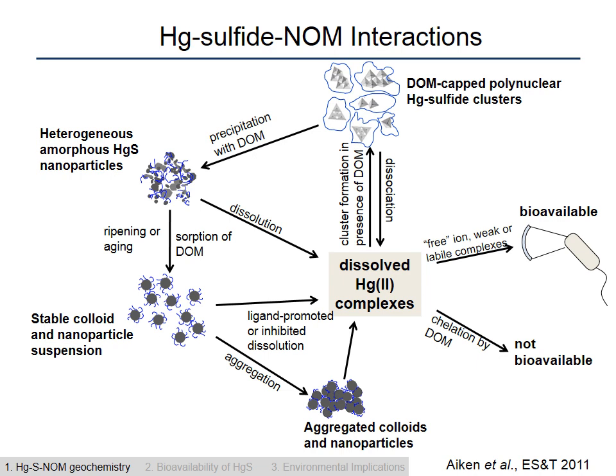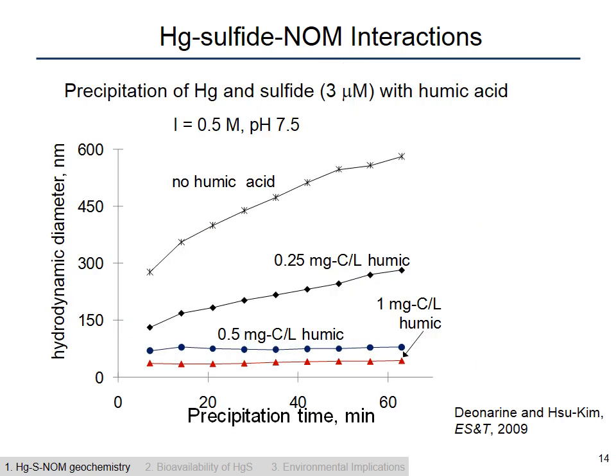So in the next slide, I'm showing you some lab experiments where we demonstrate how organic matter actually will slow the process of mercury sulfide precipitation. Here's an experiment where we took dissolved mercury and dissolved sulfide, and precipitated it in solution that contained humic acid. And the graph here is showing the hydrodynamic diameter of particles measured as a function of the precipitation time. And what you can see is that as we increase the amount of humic acid in solution, we end up getting smaller particles